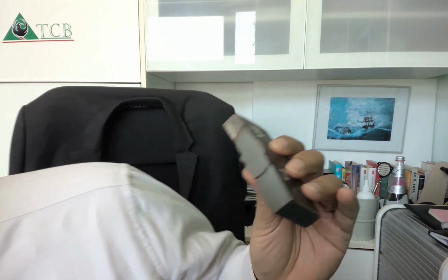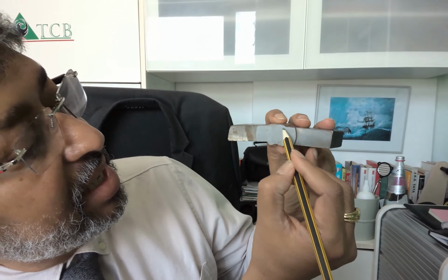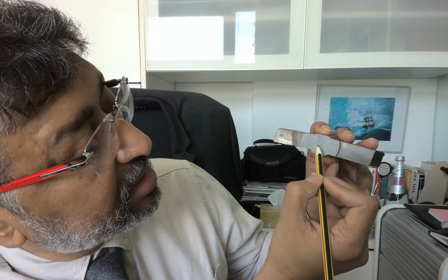This was cut from a spiral welded pipe, and this was the pipe thickness. So here, this is the weld, and you can see some area which is clear, the heat affected zone. There is a very shadowy line. So this is the heat affected zone. This is the weld deposit. This was done from both sides. There is the inside of the pipe, that was the outside. The surface has a very nice finish, done with the submerged arc welding process on both sides.